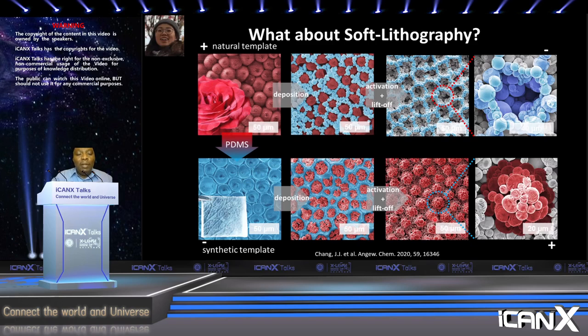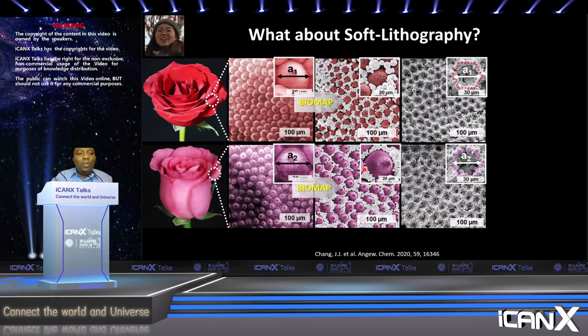Now, what is the sensitivity of this and why would we care about this? One thing that we wanted to challenge ourselves is to see how good we are at replicating the structures we are working with. So we took two cultivars of the same rose flower, a red and a pink rose. If you look at these two SEM images here, they look very similar. You don't see much of a difference until you measure the distance between, or the size of the features, and there's a really, really small feature difference.